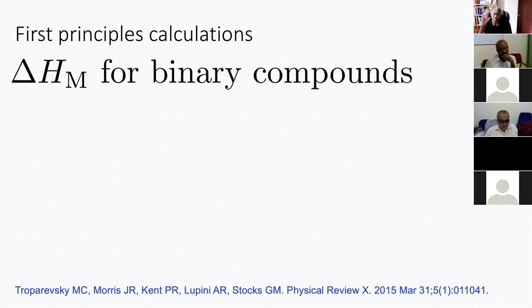So first principles calculations basically involve electron theory. And because we often don't have data, first principles calculations don't need experimental data. You can say, okay, I can imagine an FeCr2 compound. Now, what would be the enthalpy change accompanying the formation of that compound? And I can then try and see whether it is a very large enthalpy change, in which case I will get that precipitation or not. Now, compounds are very easy with first principles calculation because there is a well-defined chemical composition for the compound. It's not really possible to handle solutions where you have a wide range of composition, because that means that your supercell that you use in the calculations has to be so big that you basically don't have computational power.